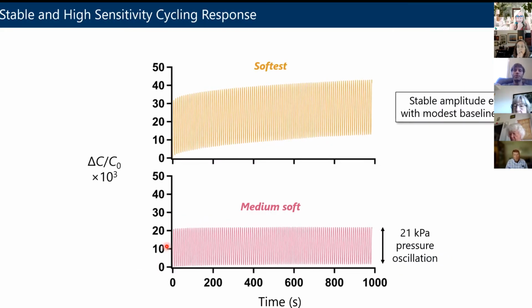You can monitor this in a different characterization tool we have in the materials research lab called a dynamic mechanical analyzer. It's basically a probe, and you can program it to jam into your sample at an applied frequency with a given amount of force over and over and over again. So you can see we're monitoring this signal, or the relative change in capacitance, over and over as a function of time when we oscillate with a pressure of 21 kilopascals, up and down, up and down.